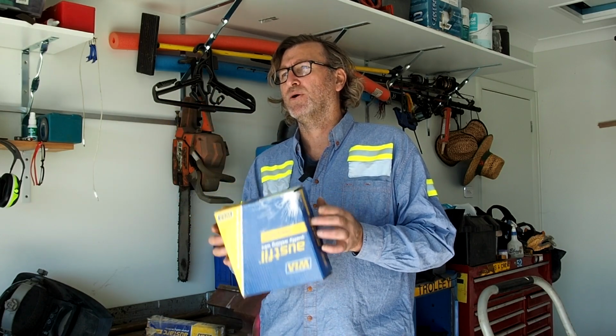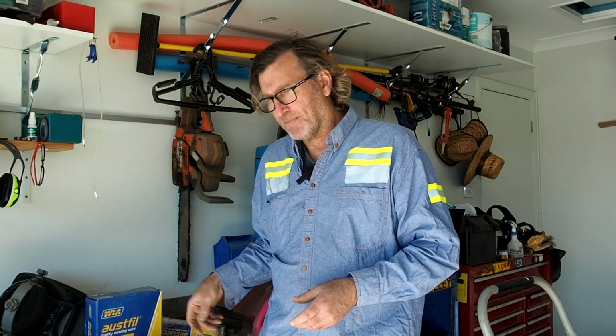Now this Austfil 11, it is a gasless wire, so you don't need any shielding gas. All the gases created to shield the molten weld pool are created from the flux burning that's moulded into the centre of the wire. So there wasn't any problem there, but what was happening was the electrode wasn't actually getting hot enough to burn the gases correctly, which meant that it was just spraying out all the molten metal from the electrode, which made the spatter, and the crack was caused because the polarity was the wrong way around, and it wasn't heating the metal up enough to put it down onto the material.